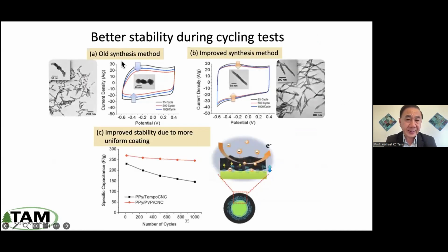So I can see here, on the left is the generation 1. As you can see, the nanoparticle coating is not very smooth, right? There's irregularity, and that's evidenced by the TEM picture. And that results in a 30% drop in the specific capacitance under 1,000 cycles.